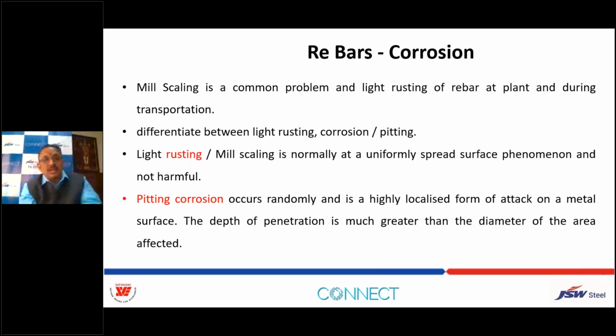But corrosion, which goes deep, and pitting, where sometimes the depth of the pitting is more than the diameter of the size you see. So it's very important. We must observe this pitting corrosion, which occurs randomly and is localized on the metal surface. So the depth of penetration is much greater than the diameter of the area. So we have to be very careful about this pitting corrosion.